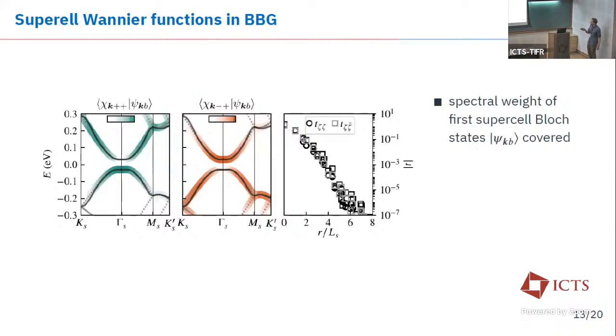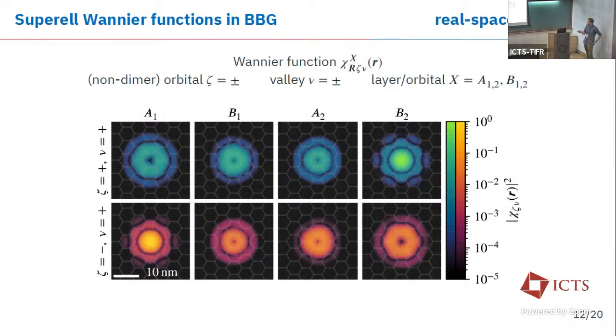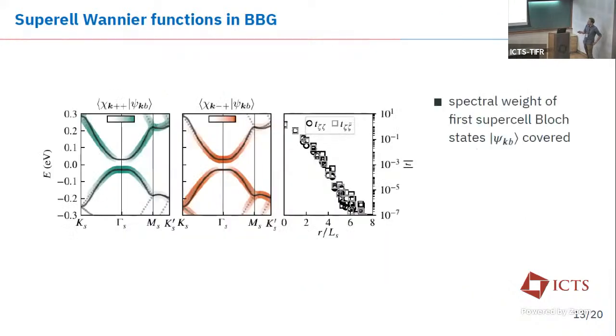And what we then do with these Wannier functions, we project them onto the original Bloch states. Now, this is the one Wannier functions plot. The blue one is the Wannier function corresponding to the B2 orbital, and the red one is the one corresponding to the A1 orbital. And we see that they have most weight in the Bloch states around the supercell gamma point, which corresponds to the valley K or K prime of the original primitive cell. And the other one, of course, correspondingly has most weight in the conduction band, and together they reproduce most of the spectral weight of all the states close to zero energy.